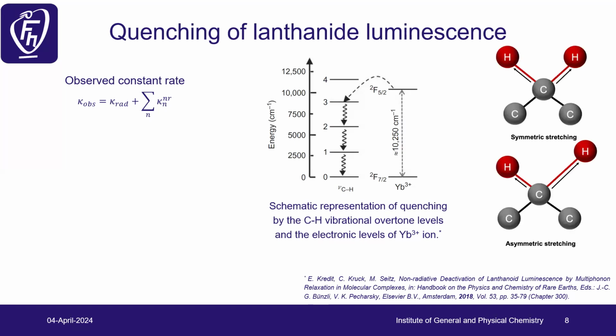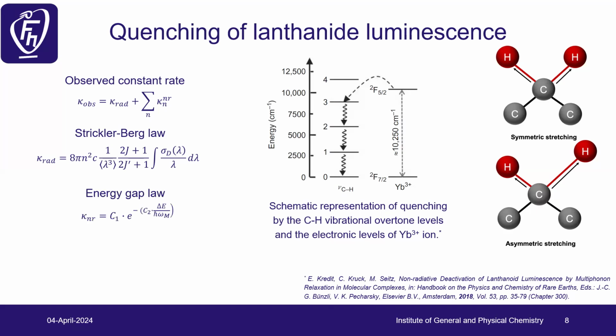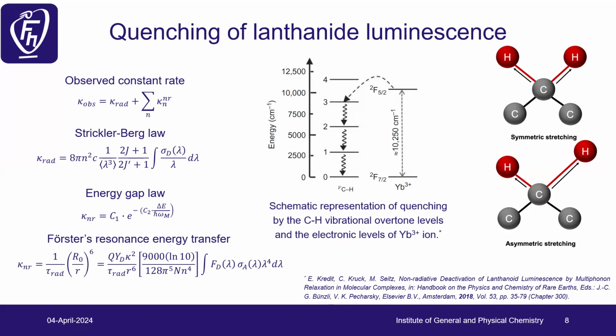Here we can see that we have some different vibrational movements, stretching of CH groups, such as symmetric or asymmetric. With the Judd-Ofelt theory, we can calculate the radiative lifetime for the near-infrared, because the same levels that are used for the emission are also absorption levels. For the visible one, it's a little bit difficult because different levels are absorption levels and emission levels. And we have a few ways. One is the energy gap law, so that we can make a difference between energies, or second is Förster resonance energy transfer, where we have the distance between the donor and acceptor, overlap, and of course radiative light.